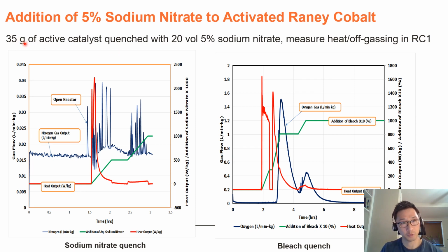So we did the same reaction as before. We took 35 grams of Raney cobalt. We activated it under 4 or 5 bar of hydrogen, but this time we quenched with 20 volumes of 5% sodium nitrate in an RC1 where we measured the heat and off-gassing. So I show the data for the sodium nitrate quench on the left and the data for the bleach quench on the right. Once we begin our addition of sodium nitrate, we do see a spike in heat, as you see here in the red curve, but the total heat is actually measured as the area underneath the red curve, and so the area underneath the red curve on the left is much less than the area underneath the red curve on the right.